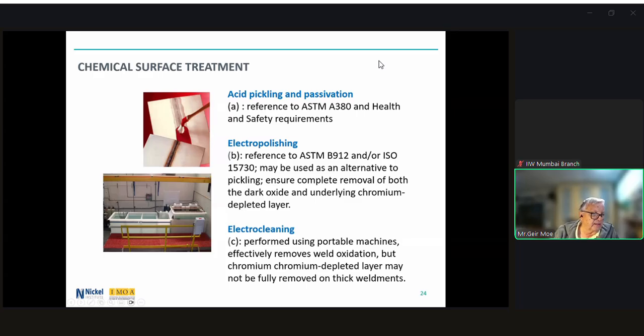In addition to pickling, heat tint and surface contaminants can be removed by electropolishing and electrocleaning. Electropolishing is typically achieved by immersion in an electrolyte, where an electric current selectively removes material with lower corrosion resistance and thus ensures complete removal of both dark oxide and the underlying chromium depleted layer.